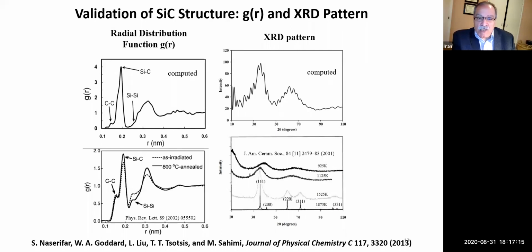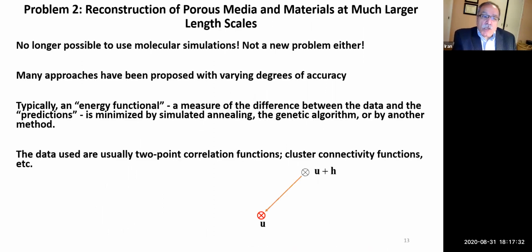On the right, you see the X-ray diffraction pattern. Again, they computed on the top and the measured on the bottom. They agree, in particular, the location of the peaks, which is the most important thing, agree completely, and this was published in 2013. Okay, so that's reconstruction at the smallest scale.